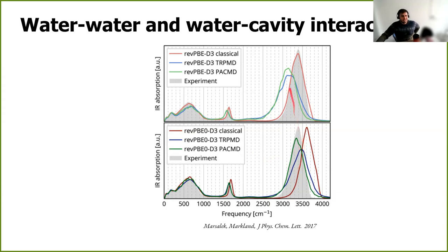Now, if you were to analyze this particular plot just in terms of the frequency of the stretching mode, and if you had some experience in interpreting spectra of water, what you can infer here is the anharmonicity of the OH bond. We all have heard about the Morse potential, right? So if you have a Morse potential, then as you increase the anharmonicity, you see a red shift in your vibrational spectra.